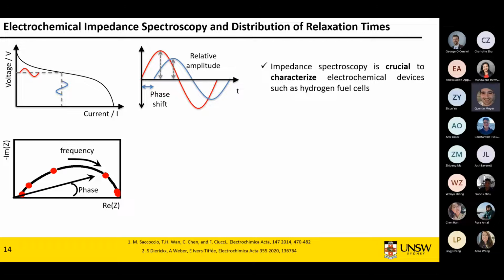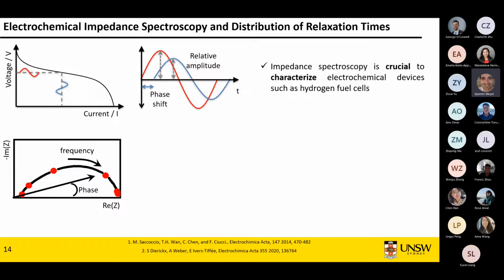You get a cute semicircle, and you don't really know what to do from there. You often get stuck. So you can do some modeling, find some equivalent circuit. You can do a physical-based model. But the problem of these techniques is equivalent circuits, 1,000 of them can actually fit your system, and you actually end up quite struggling to analyze it. Physical-based models, it's even worse because you need to go into maybe 50 equations to fit your Nyquist plot. So that can be quite challenging to do.